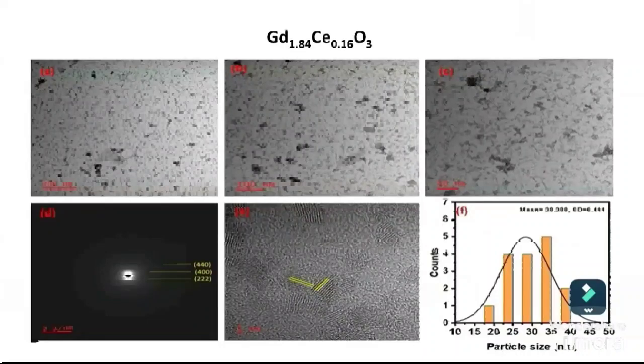So this is a slide for 8% cerium doped gadolinium oxide. Again, the shape is pseudospherical. The shape has not been changed, but the size has been reduced. Now the cerium doped gadolinium oxide has a size of 28.288 nanometers.